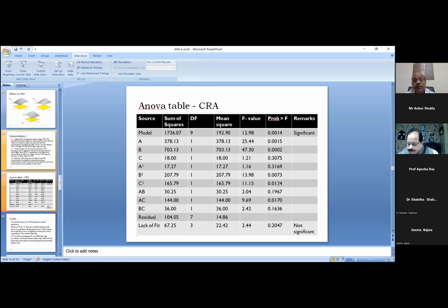So this is the ANOVA table, and the model is significant. As the result shows, you get the p-value of 0.0014, a very, very small value that shows that the model is highly significant. And the lack of fit is not significant. That is what we wanted, because we didn't want any kind of lack of fit. So the model is absolutely appropriate to the experimental work that is done.